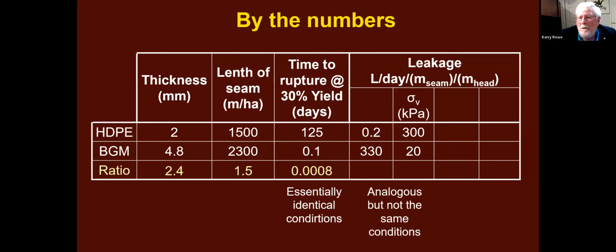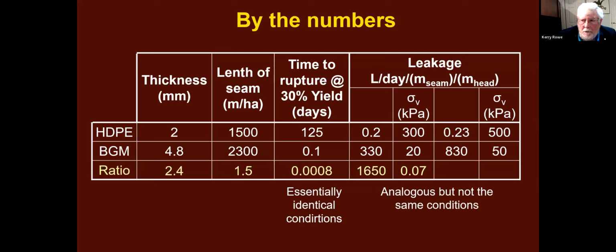If we now look at the BGM, we only tested at 20 kPa. I said these are not apples and apples comparisons, but our leakage is 330 or 1,650 times higher. We go to 500 kPa. In our HDPE case, our ratio is 0.23. We go to 50 kPa, it's 830 for the BGM as our leakage. In normalized terms, a 3,600-fold difference.